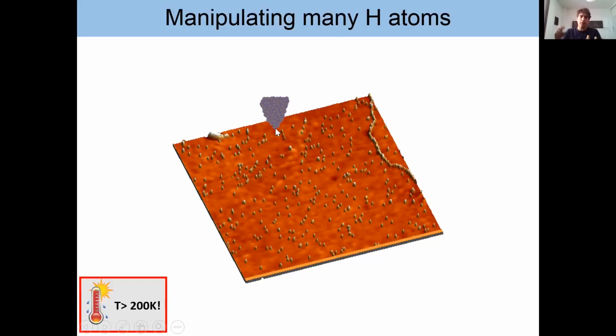What you need to do is first hydrogenate your graphene. We do this by exposing graphene at room temperature to atomic hydrogen. Okay, so this is the result you have. It is very stable. And then we can do our manipulation experiments, but an important remark is we need to be at high temperature. The manipulation only works at temperatures beyond 200 Kelvin, at least for us. So now we are at this high temperature, usually 220. Then we go with the STM tip, we approach, we apply 4 volts, we make a trajectory, and while we make a trajectory, hydrogen atoms get trapped along the path followed by the STM tip.